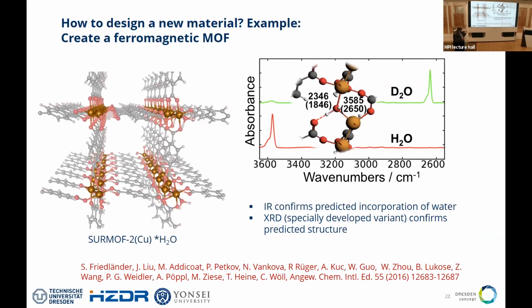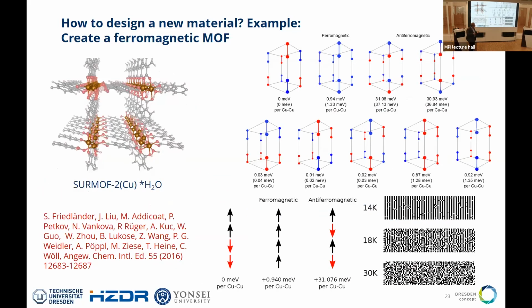Actually, what happens is that the water kind of sneaks into the structure, dissociates, binds to the copper atoms and makes some additional bridges. It looks like that then. So we have this kind of very intriguing structure. And we could confirm, well, we were predicting that. It was confirmed with infrared, with hydrogen, and with deuterated hydrogen.